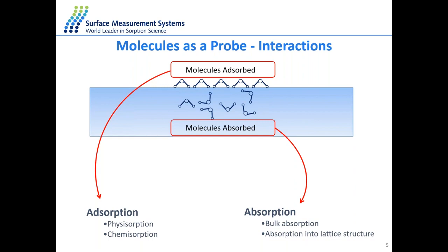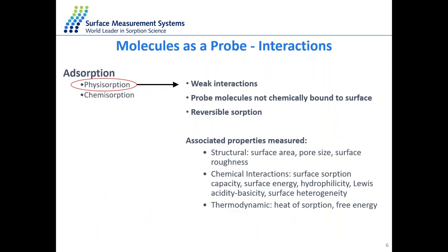So there's two ways molecules can interact. They can either adsorb, and in this case, we're looking at more physisorption and chemisorption, or they can absorb into the bulk and into the lattice structure of the sample. So if we're looking at the adsorption, we're looking at more weak interactions. The probe molecules may not necessarily chemically bind to the surface. And in this case, we're looking at more reversible sorption. And with this kind of property, we can understand structural properties of the sample, so looking at surface area and porosity. We can also understand more chemical interactions, such as surface sorption capacity, surface energy, and heterogeneity. We can also understand heat of adsorption and free energy of the samples too.